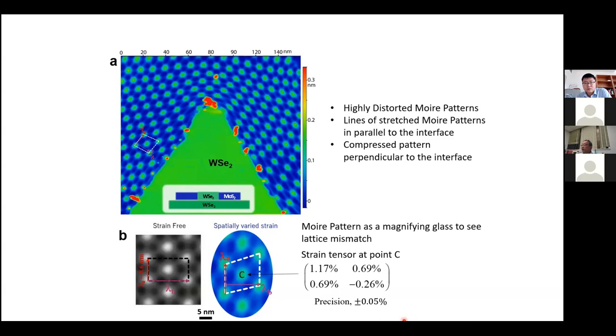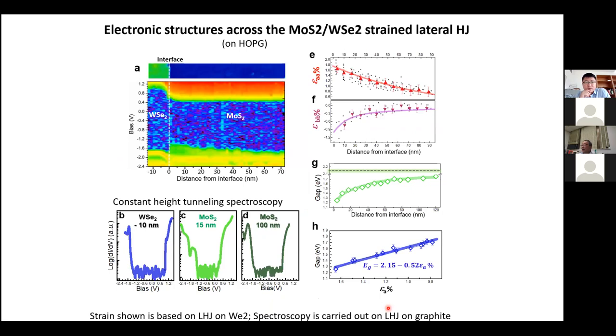In this case, you can even determine a change of the lattice constant as small as 0.05%. And the reason you can have such high precision is not because STM gives you such high precision, since STM will give you about 1 to 2% precision. It is because of this amplification factor of the moiré pattern that gives rise to this high precision in determining the strain. And the strain, of course, has an impact on the electronic structure. You can see the MoS2 band gaps go narrow, narrower and narrower. And then we can determine the band gap narrowing as a function of the strain.